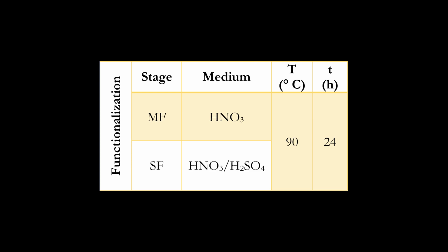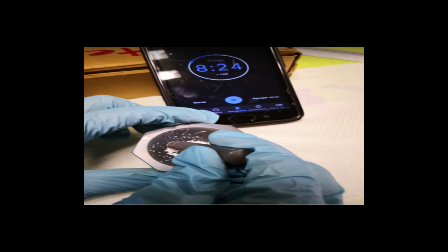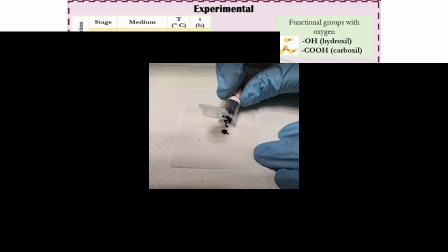Once the carbon nanotubes were functionalized, a mixture of the functionalized carbon nanotubes with the molybdenum hexacarbonyl precursor was prepared, mixing them for 10 minutes with the help of an agate mortar. The mixtures were prepared with different content of molybdenum precursor to propitiate molybdenum trioxide carbon nanotubes nanostructures with different molybdenum content in the final product.